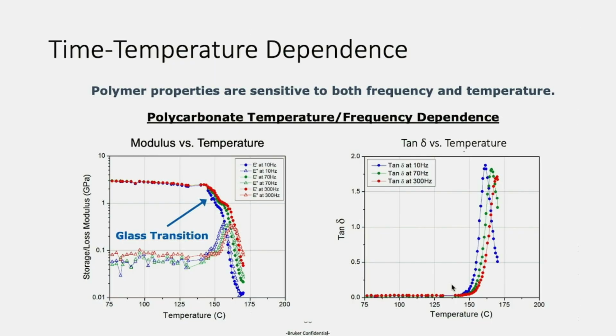Here is another example, polycarbonate. We can see the Tg. If we look at the tan delta, it's sharper. The Tg is around 150, 160. So this is very useful for us. Some people will say, I can test the Tg by TMA. That's easy, right? But how can you test the Tg of a thin film? If you coat a film that is very thin, only a few microns or a few nanometers, it is not possible to pull off the film to use a TMA, right? The nano indenter is the only solution that can measure the Tg of a polymer at the micro and nano scale.